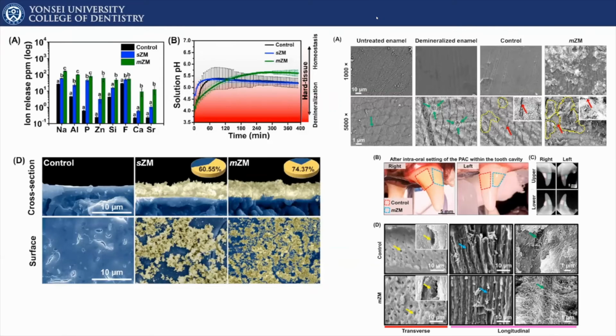In terms of ion release, as I said earlier, the addition of zwitterionic materials into glass ionomers for some reason increases ion release. But more surprisingly, when we have multiple different zwitterionic materials, the release is much more dramatic, as you can see here. And this was evident in solution pH, where the neutralization of the pH was different in pattern when we have single or multiple zwitterionic materials. When we look at the apatite layer formation, the control did not have any apatite layer formation, but the single zwitterionic material had apatite layer formation. But when we have multiple zwitterionic materials, the layer was much thicker. And this was evident with ex vivo studies, where we used demineralized animal teeth, and also in vivo studies with a canine model. The multiple zwitterionic materials certainly have remineralizing and mineralizing effects.